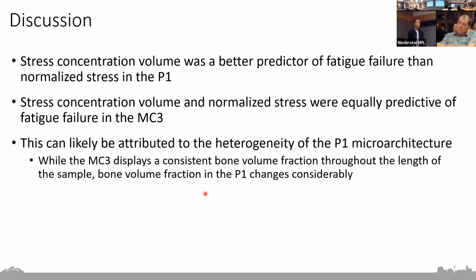So overall, I think identifying some of these microstructural features that are most relevant to the fatigue process can help us clarify the underlying mechanisms of this fatigue process. And I think that's really important to understand before we move towards predicting these fractures. So we found that stress concentration volume was a better predictor of fatigue failure than normalized stress in the P1 bone. But we found they were pretty equally predictive of fatigue failure in the third metacarpal. And we think this can be attributed to the heterogeneity of those P1 samples in terms of their microarchitecture.